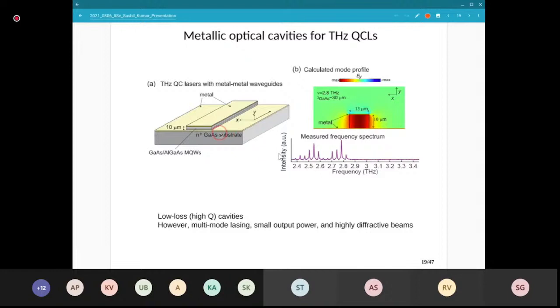The reason it works okay is because metal is not very lossy still at terahertz in terms of optical loss. Obviously, it's much less lossy at microwave frequencies, and terahertz is also not very lossy. As you keep going higher and higher in frequency, or shorter in wavelength, when you reach near infrared, it becomes quite lossy. A lot of people are doing research on plasmonics at near infrared or visible, but as everyone who works in that area knows, metal is very lossy. Typical loss for metal at our wavelength is about 1 to 2 or maybe 5 inverse centimeters, which is about 10 to 20 dB per centimeter of travel of light. So probably around 10 dB or even less per centimeter. That's not too bad because our cavities are only 1 millimeter long.